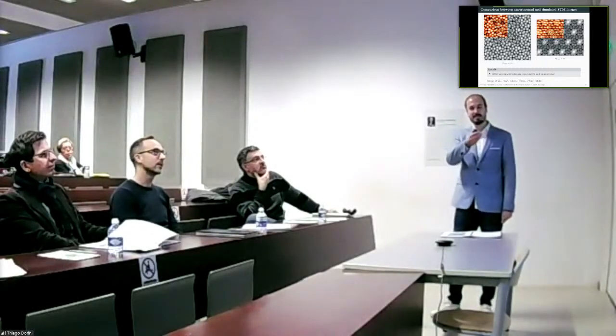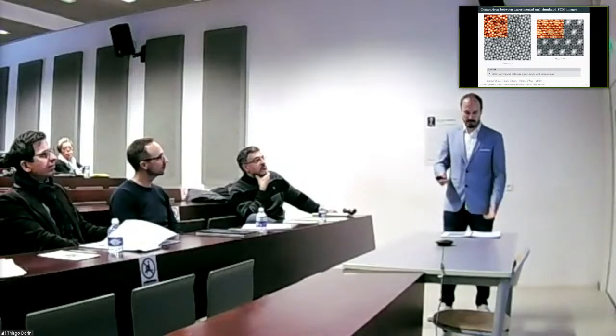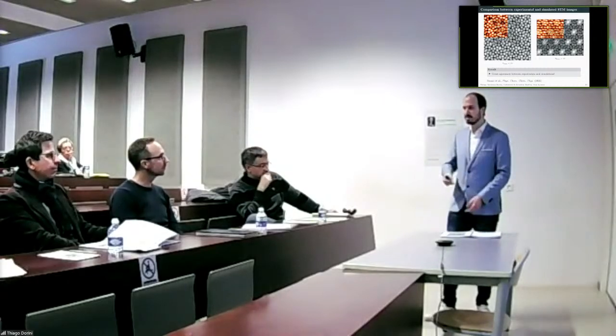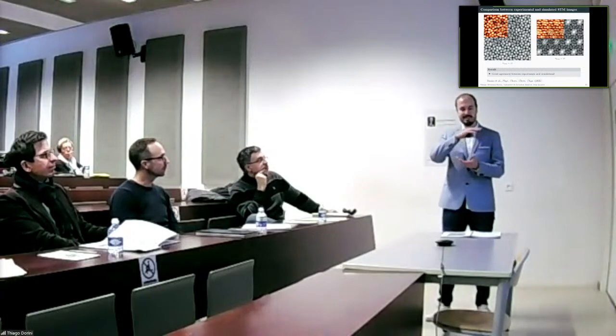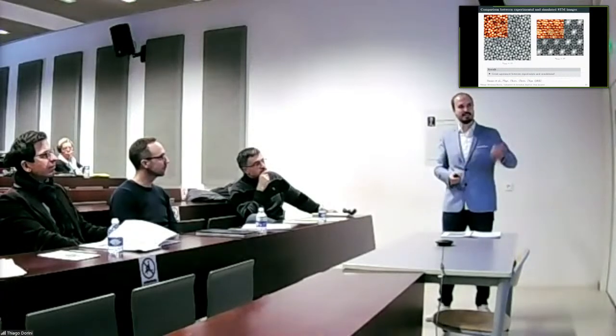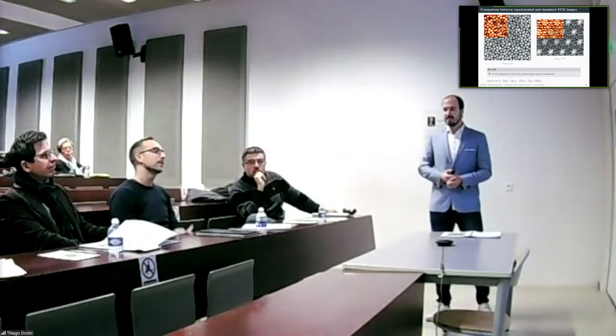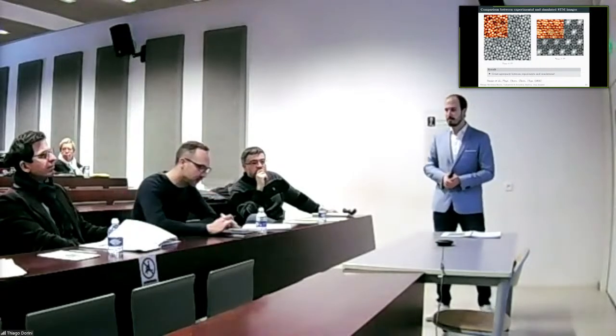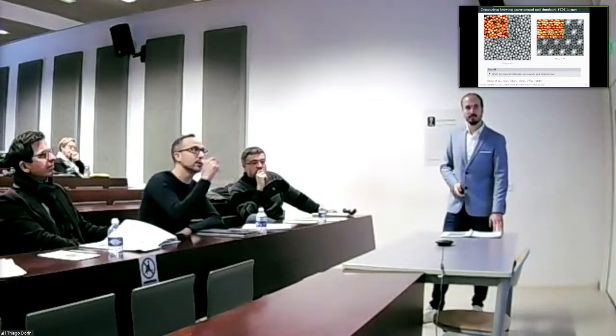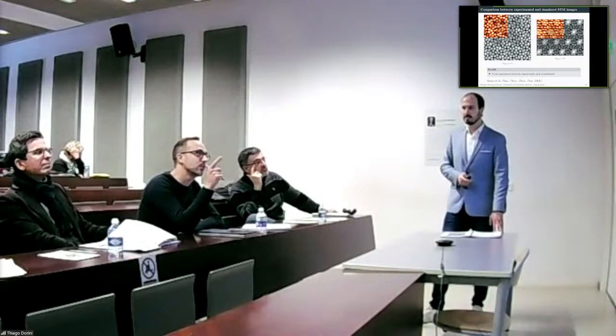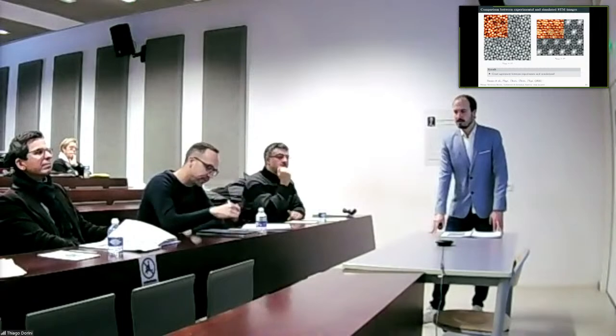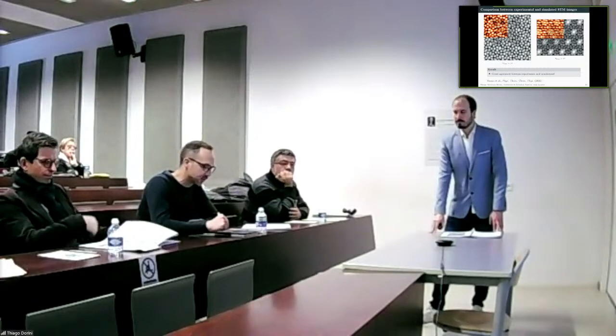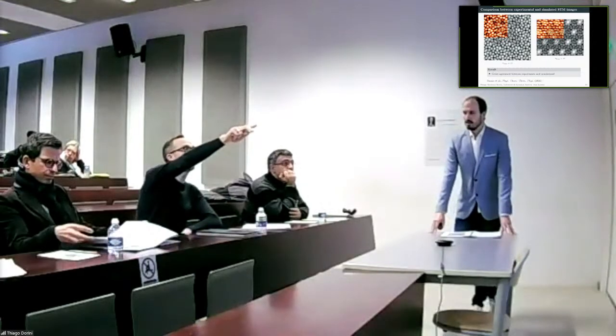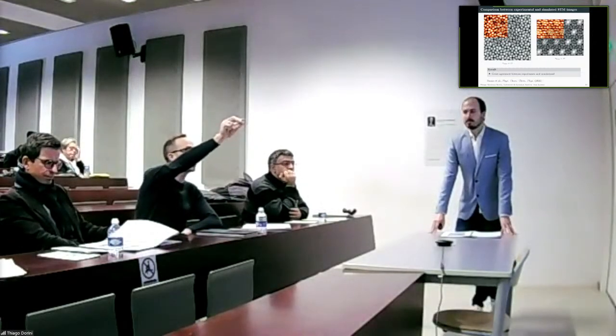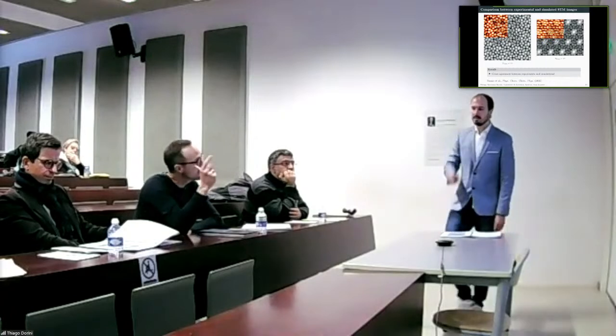It seems to me that in this approximation, the most important thing, well, first we need to have a non-zero density of states, and the heights. Height is the most important parameter to see the electronic features. In this thesis, there is the other STM image you calculated for the hexagonal approximant, but without the decoration of the centers. Yes. And in there you find systematic contrast variations here and there. So 2 pairs of the atoms in between these flower motifs are much brighter than the rest. Yes. What is different at these places?